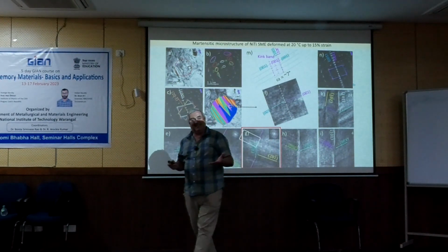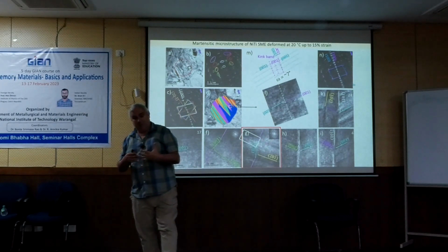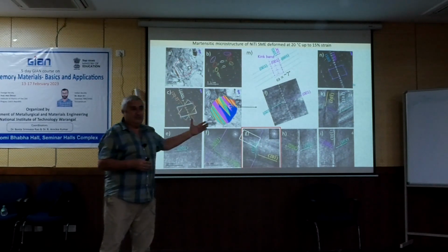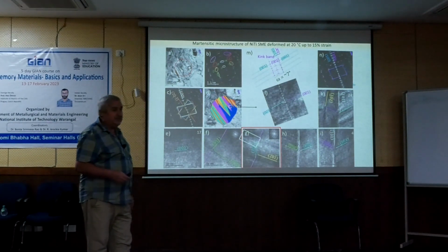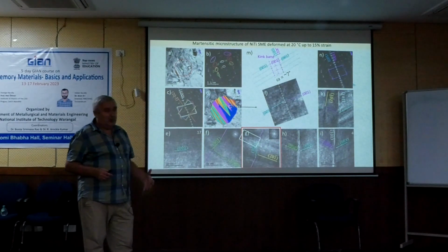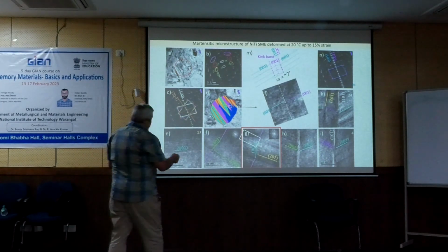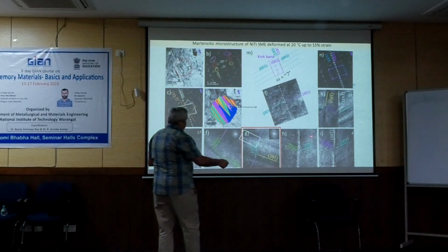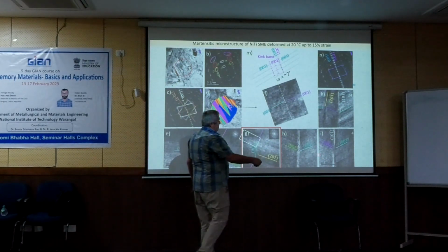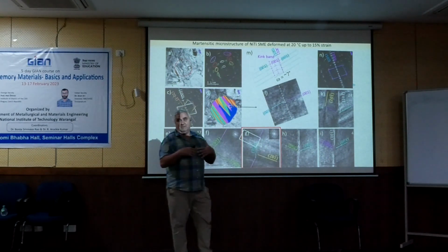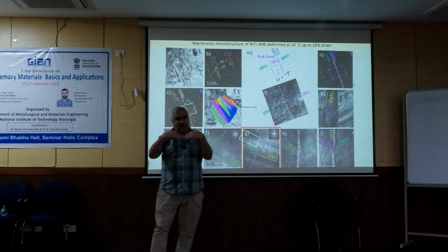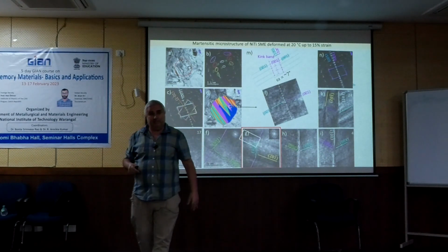So it explains the observation which I was so surprised by, how it can be that there is such kind of mirror symmetry. The condition doesn't have to be a mirror symmetry of the lattices. There is no mirror symmetry of the lattices. There is mirror symmetry of shears, which is recorded as mirror symmetry of the traces of 001 planes.